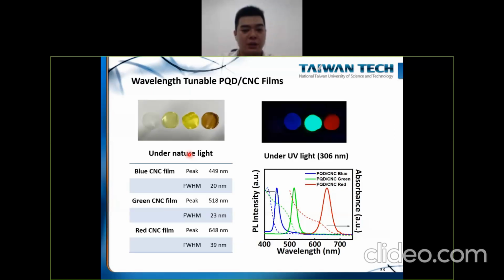So we come up with these hybrid films with different light emission wavelengths, from 449 nanometer all the way to 648 nanometer. And actually, the red CNC film is still an ongoing study, because other than the photo-induced aggregation problem, it exhibits some phase transition problem. So this part is still ongoing in our lab.